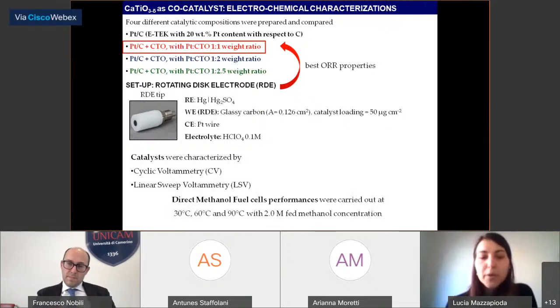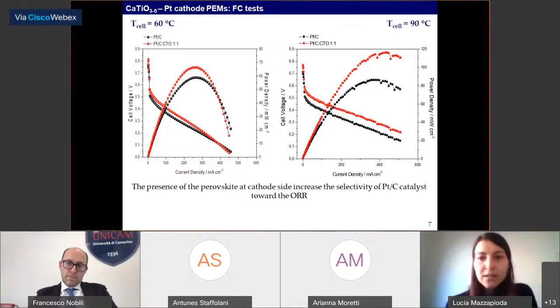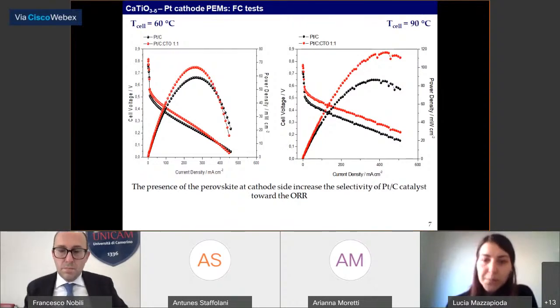at 3 different temperatures with 2 molar methanol concentration. Due to time restrictions, I will just show you the last condition studied, where we can see how the presence of this perovskite at the cathode side improves the direct methanol fuel cell performance. Especially, it is able to increase the selectivity of the platinum-carbon catalyst toward this reaction, showing a lower loss of potential, in particular in the activation and the ohmic regions.